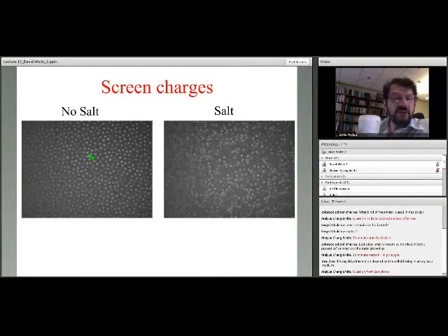It's easy to do it in an aqueous medium because then you can use charge, which gives you a relatively long-range interaction. In actual fact, charge can also surprisingly play an important role for interaction between particles in non-aqueous medium, for example in oil, but in that case the dielectric constant is much less, and so the range of the interactions is, if anything, much longer. So you can still see charge effects in oil, but they're actually much easier to see because the typical range of the interactions becomes a factor of about 10 larger than what you see in aqueous medium.